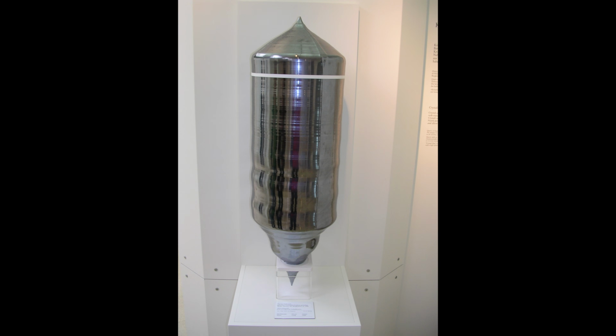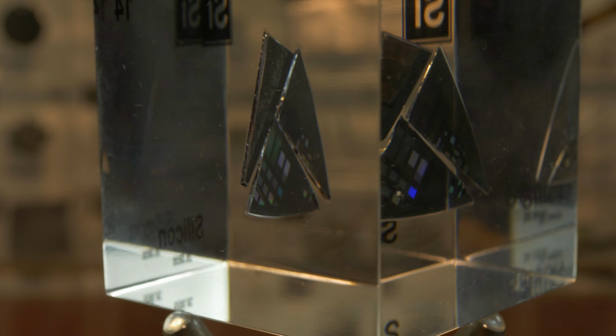By carefully controlling the temperature and pull rate, you can grow a cylindrical silicon ingot, or boule, that is a single crystal, often up to 200 to 300 millimeters in diameter, 8 to 12 inches, and perhaps 1 to 2 meters in length. This looks like an immense shiny log of metal, but remember, it's not a metal, it's just that look. It weighs hundreds of kilograms.